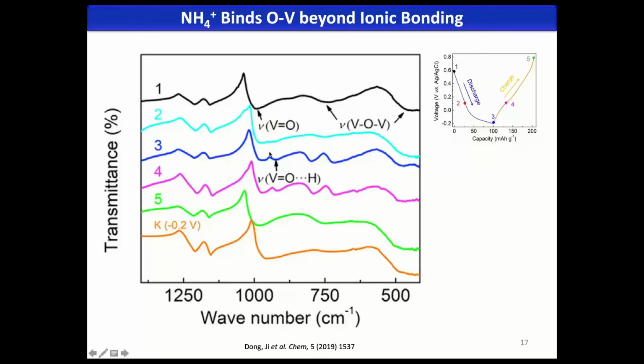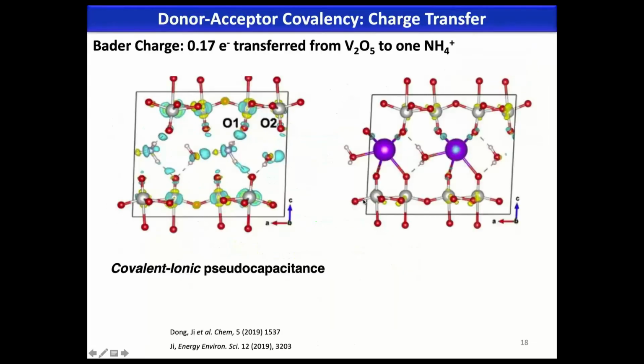So you have some kind of directional behavior in terms of their reactions. Whenever we have directional behavior, we call that covalency, right? For ionicity, it's actually radiating to all the directions. We don't have direction in terms of the interactions. And you can see that this is really due to the hydrogen bonding. The peaks are splitting, right? That's very interesting. So my collaborator, Professor Greeny, in UC Riverside, he helped with the computation here, and this is the differences between ammonium and potassium.